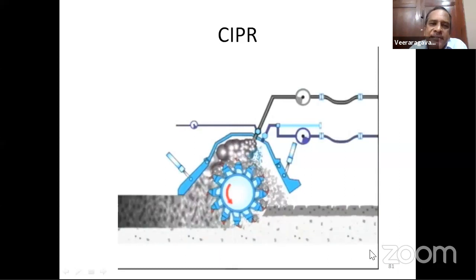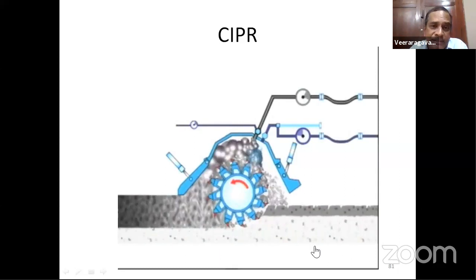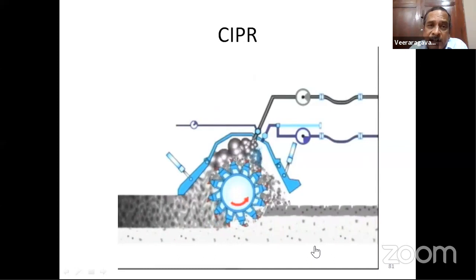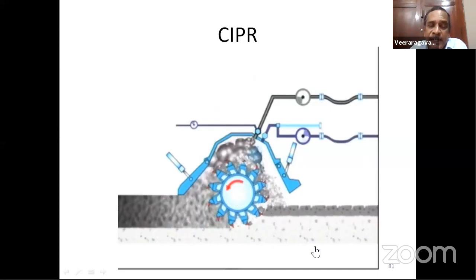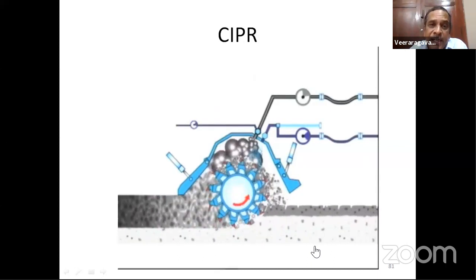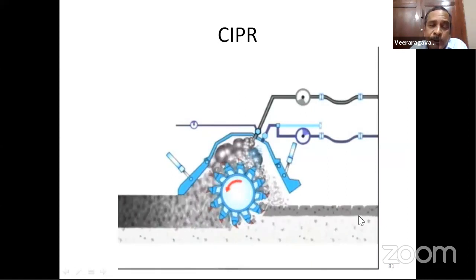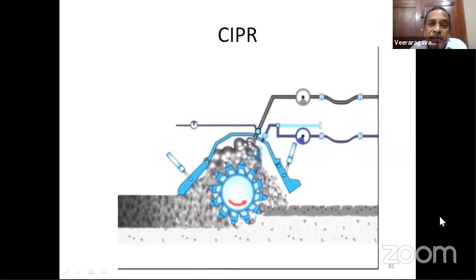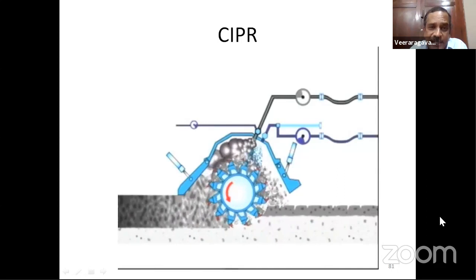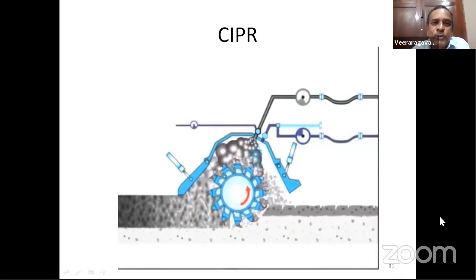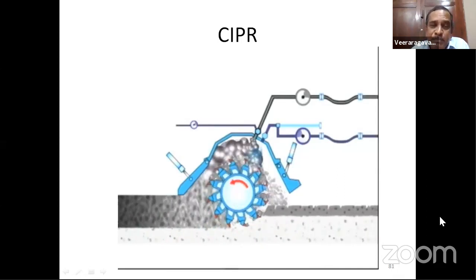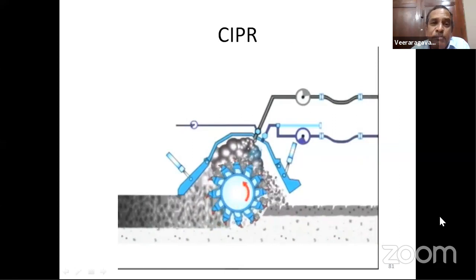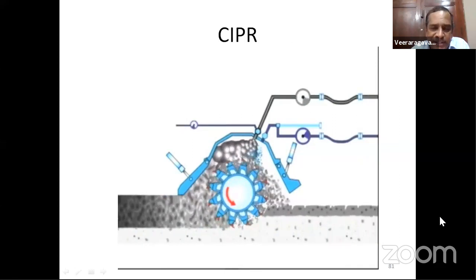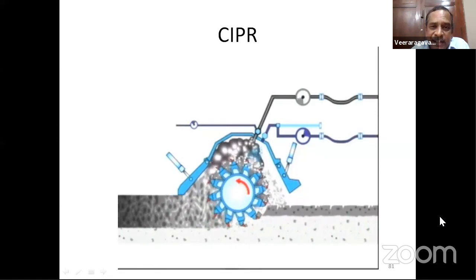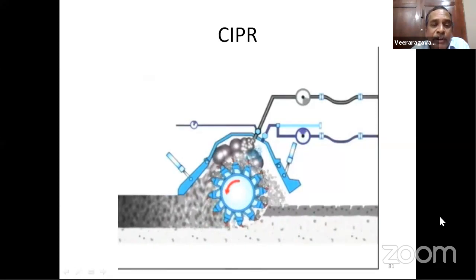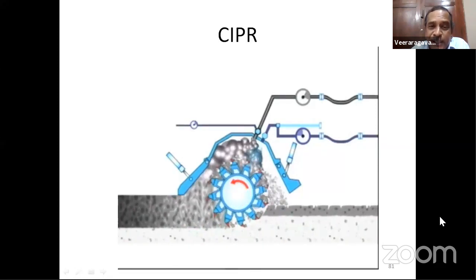So if you consider the strength of this layer in terms of modulus, the conventional granular material can have a modulus of 250, 300 MPa. But this, we found, can give you a modulus of nearly even 1,000 MPa. But considering the variability, IRC restricts it to 600 MPa, but still, it is much better than any of the other layers. And we constructed, for the first time, I did the mix design for the Chennai Tada Highway, wherein we have provided this foam bituminous mix in the year 2011.